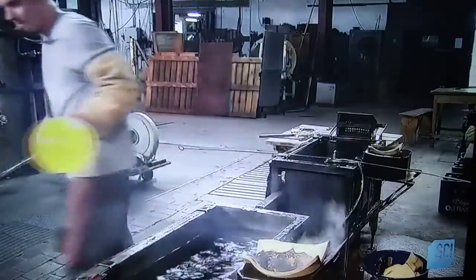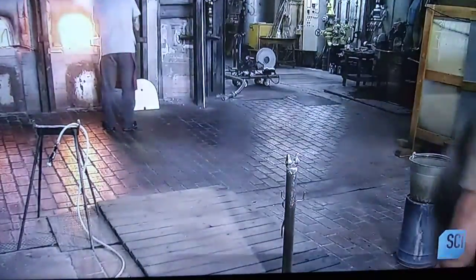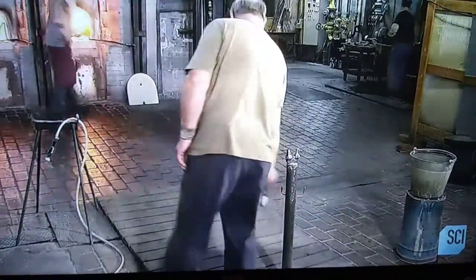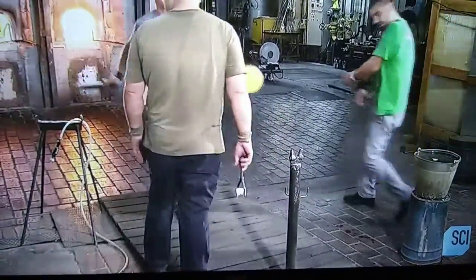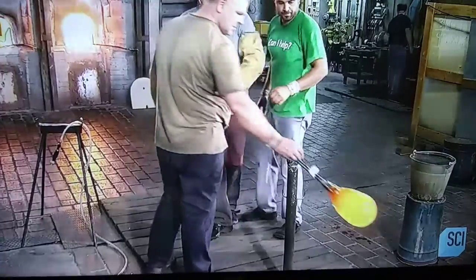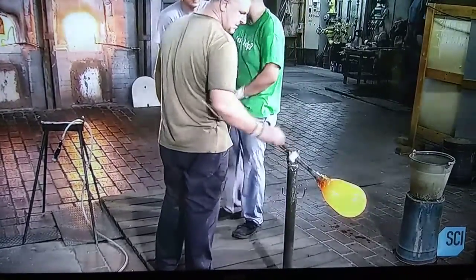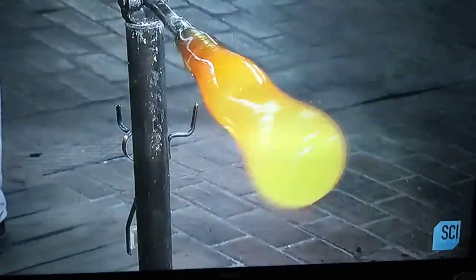The molten glass cools rapidly once it comes out of the furnace. If the temperature dips below 1800 degrees, it's no longer workable, so the team must work quickly and reheat the glass repeatedly. Another assistant lubricates the blowpipe, so it will rotate easily on the support stand. The starter hands the glass over to the master glass blower.